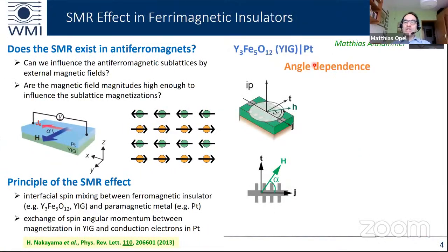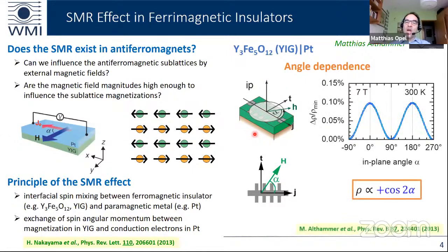So we measured in a double layer of YIG and platinum the angle dependence of the magnetoresistance. For this, we were applying a magnetic field H, and we were rotating this magnetic field in the plane of the sample, and we saw a characteristic oscillation of the resistivity as a function of the in-plane angle. The effect size is about 10 to the minus 3. And we found that there is a characteristic angle dependence of the resistivity, which is proportional to cosine 2 alpha.